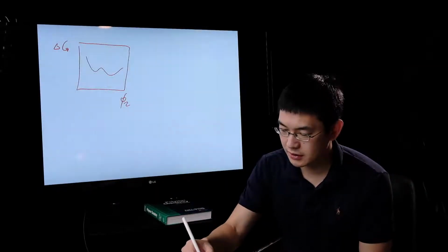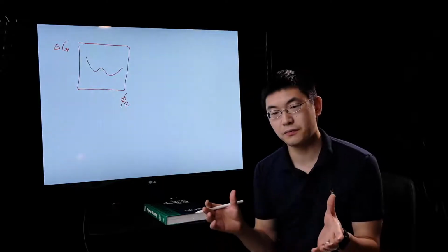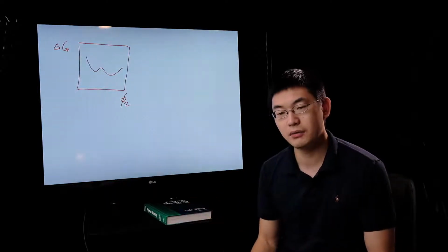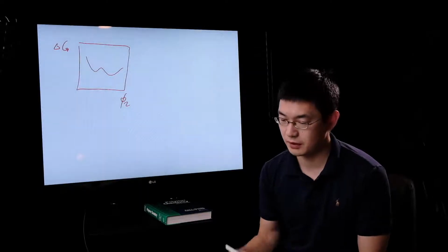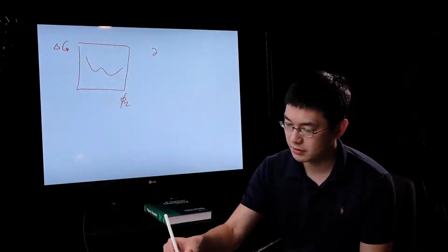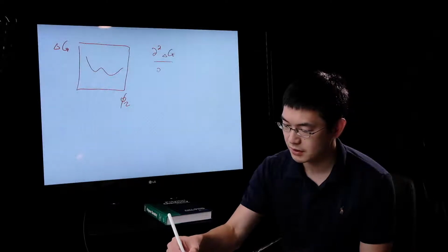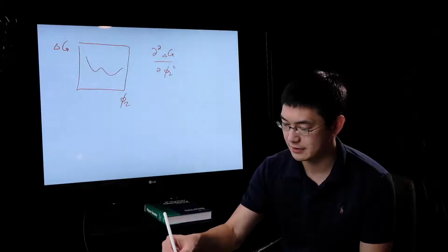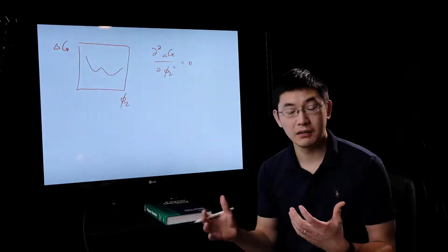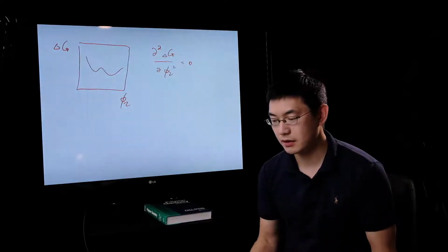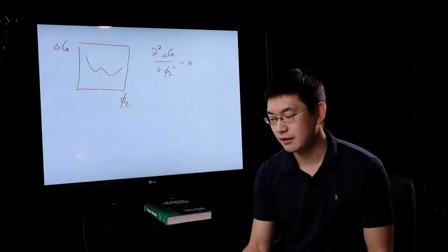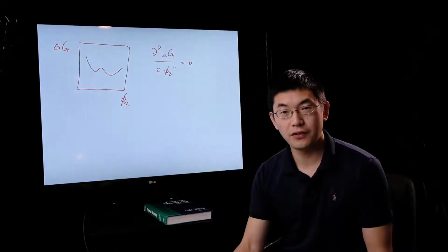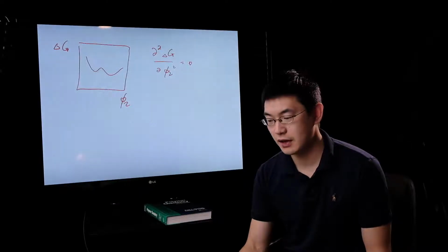We discussed that whether this curve is concave up or concave down directs whether the system spontaneously phase separates or not. And we discussed that if we take the second derivative of delta G with respect to phi or x, no matter what it is, it will give you similar results. This will define the phase behavior for a spinodal curve, okay?